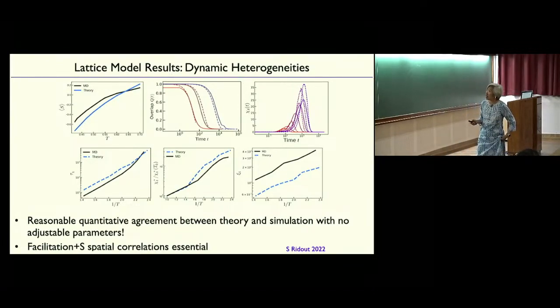There's no elasticity here. And here are the results, okay? So the theory is the blue, the MD simulations are the black. And so the average softness, not bad, you know, agreement, okay? Here's the overlap parameter. The theory is the dashed lines, the simulation is the solid. Again, pretty good, okay? Here's the chi4, the kinetic heterogeneity.